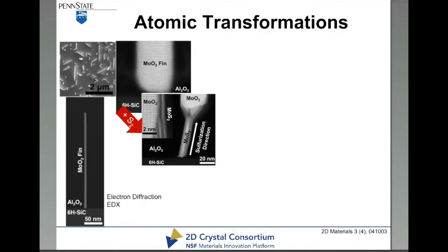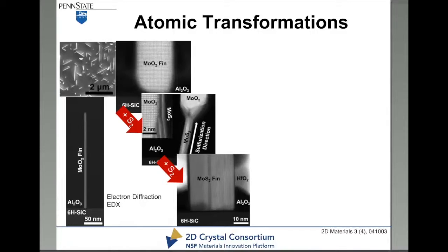And the sulfur has to be able to come in and migrate through a particular route. And that happens to be at this interface between the substrate and the fin, where you actually have van der Waals gaps, et cetera, that are exposed. And now sulfur has a very high probability of diffusing up through these layers, and we get this transformation of MoO2 to MoS2. And if you continue the sulfurization, you can get these beautiful MoS2 fins that are vertically forming out of the surface. So using TEM, we're able to start thinking about mechanistic ways of the phase transformations,